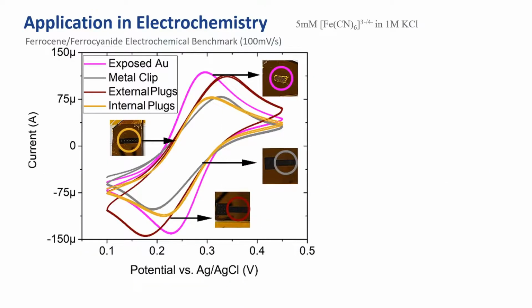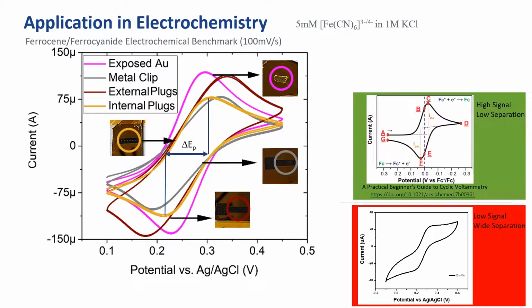To demonstrate the necessity of reliable, controlled contacts near to the active region, we carried out demonstrative cyclic voltammograms using the well-established ferro-ferricyanide reference reaction. For those unfamiliar, the key feature to look out for is the separation between the oxidation and reduction peaks, called delta EP, and the intensity of the peak above the background. These features can be used to determine how far a system deviates from ideality. We want to see highly intense signals with spacings of approximately 56 millivolts.